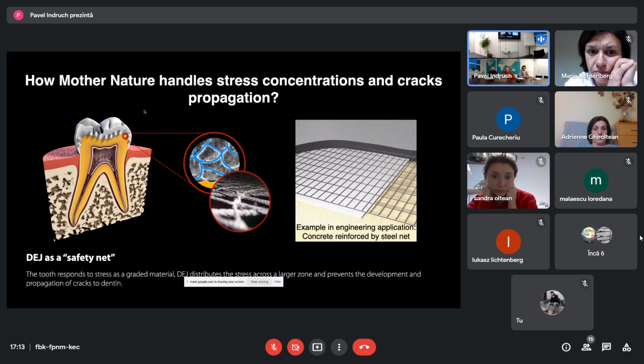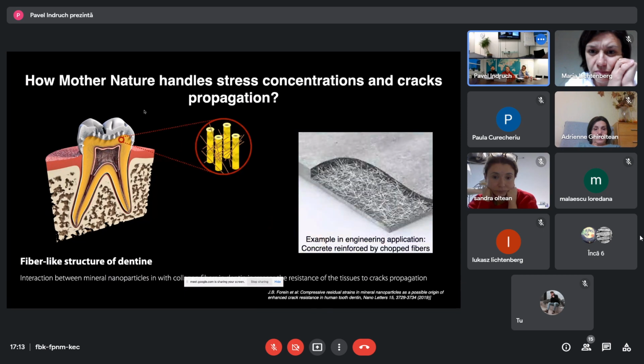The example of an engineering application of this would be a concrete structure reinforced by a continuous steel net. This is the technology used in skyscrapers and everywhere. And it's clear that it works. Also, the fiber-like structure of the underlying dentin increases the resistance of the tissue to crack propagation. The energy of cracks can be dislocated on the surface of collagen fibers, avoiding the propagation of cracks to the root and to the apex of the tooth.